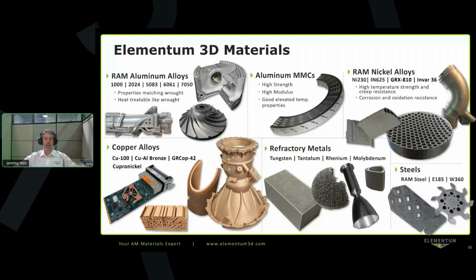So to expand a little further on our family of materials, we have a family of aluminum alloys, many of them based on wrought alloy products that otherwise would be unprintable, but also based on composite type products and high strength custom alloys that otherwise would not be producible by additive manufacturing. We have a family of nickel alloys, including a nickel alloy 230 RAM product, Inconel 625 RAM product for improved performance. With the 625, you can get performance comparable to a 718 type material without the need for the complex heat treatment that 718 would require. GRX-810, as I mentioned. We've also worked with other more customized nickel alloys like Invar 36, for example.